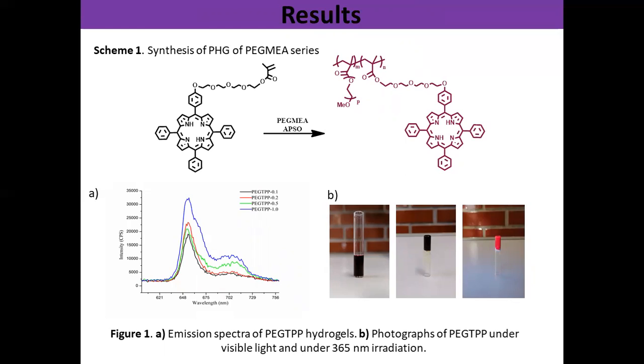The optical properties of the obtained hydrogel were studied by fluorescence spectroscopy in solid state, where we can observe an emission band at 655 nanometers in addition to an evident purple coloration due to the presence of porphyrin, and a clear emission when irradiated with UV light.